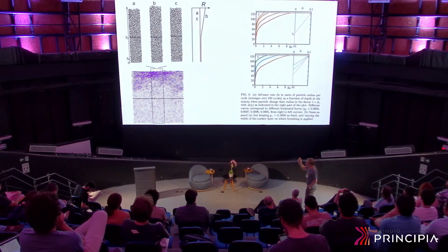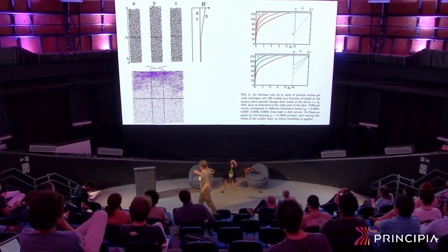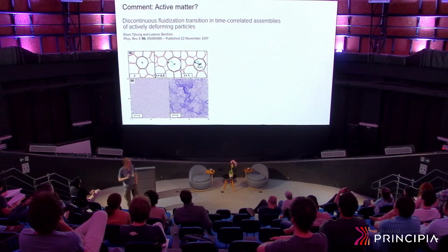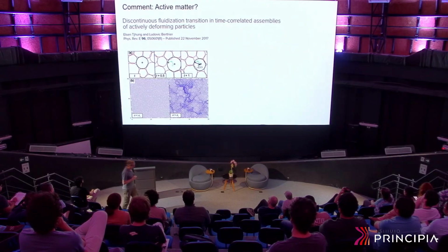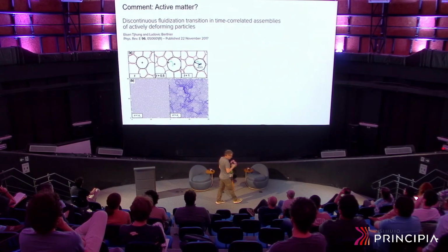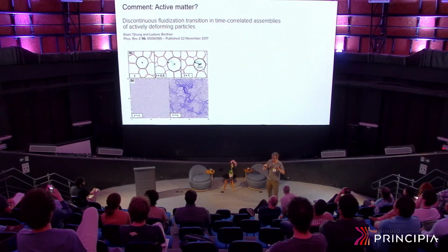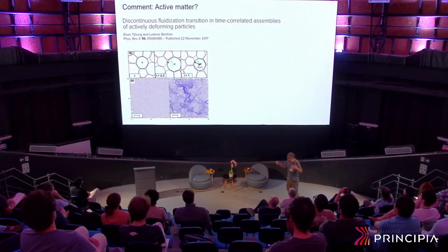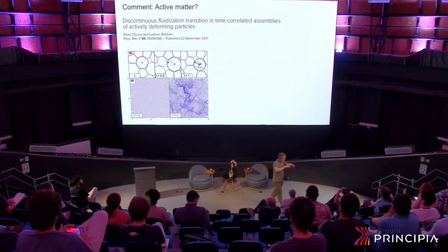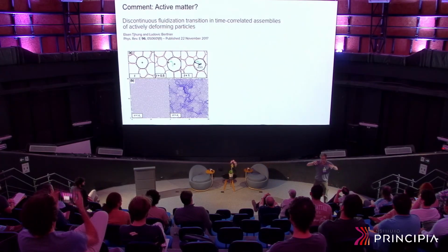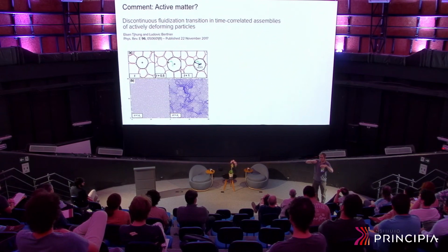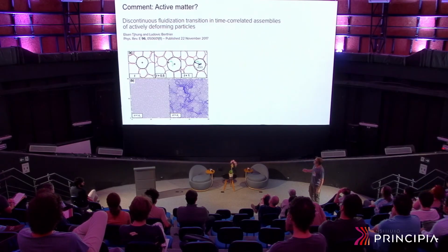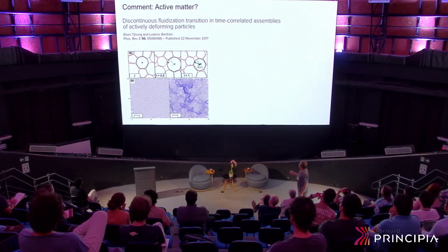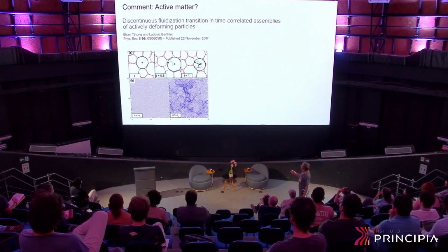Well, this is a flavor of the result of the numerical simulations, and now, because there are many people here that are interested in active matter, let me say that this kind of model, totally independently and actually before our work, was proposed, or some similar model was proposed, for something that could be called an active system of particles. If you consider that these disks increase and decrease their radius, but not all together with the same phase, rather with the same period but different phases, you have a system in which the particles are changing size. For instance, from this configuration this particle increases in size and then decreases, but others, probably here, decrease the size up to here and then increase. So this is not in phase.